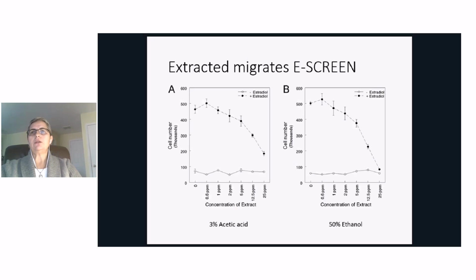To make sure that this was actually due to lack of cell proliferation and not cell death, additional plates were prepared, and the same concentration of estradiol was added to the plates to induce full, maximal proliferation. So these are the plates that have not only the extract from the polymer, but a single dose of estradiol, and as you can see, at least up to 2 parts per million there was no decrease in the cell proliferation, and then there was cytotoxicity observed at higher concentrations. So basically, once again here, we see that the extract from the polymer did not increase cell proliferation.